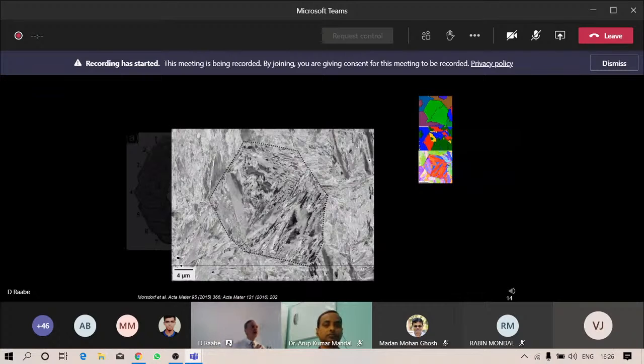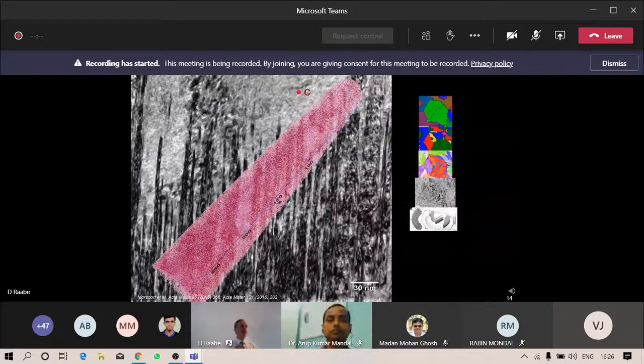And in TEM, you see now the very fine laths that are in part as fine as a carbon nanotube, and you see overlaid here by an atom probe measurement the positions of the carbon atoms, which, even in martensite, we know the carbon is not fully quenched in, as we write in textbooks, but the carbon can always, during quenching, do a couple of atomic jumps, decorating, for instance, the internal interfaces, such as the lath interfaces or the dislocations and so on. So you even have classical iron-carbon martensite in such a DP steel with a slightly higher than expected carbon content that is decorating the defects.